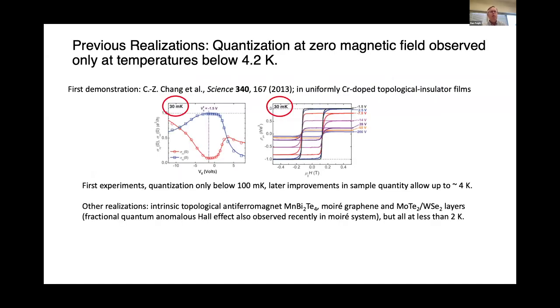So just to give credit to the first demonstrations by C.-Z. Chang, the first measurements were below 30 millikelvin or so, seeing nice quantization and zero conductivity states too. There have been various improvements in materials quality that have got the Hall quantization up to originally about 2 Kelvin and very recently up to about 4 Kelvin or so. Very nice work from Rutgers. And there have also been other realizations other than magnetically doped topological insulators, but all those still remain quite low temperature, below 2 Kelvin or so, where the quantization of the Hall conductivity is seen.